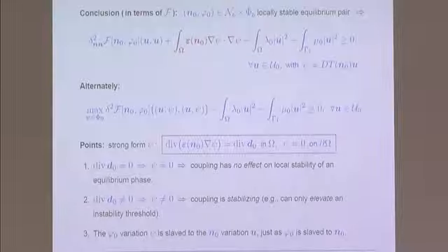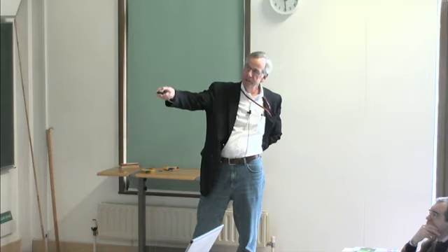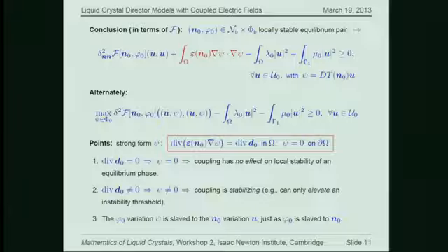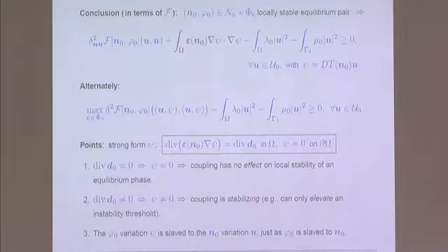So here you can draw a couple of quick conclusions. If the D naught vector field is divergence free, then your right-hand side here is 0, your boundary conditions are 0, you have a homogeneous problem, and your psi solution has to be 0. So this extra term that appears in your eigenvalue characterization, which is a positive definite term, and can only boost things upwards, is 0. So it really has no effect at all.